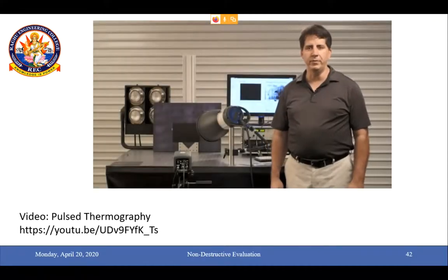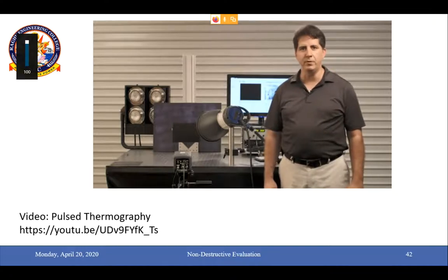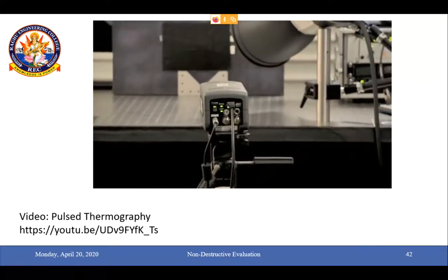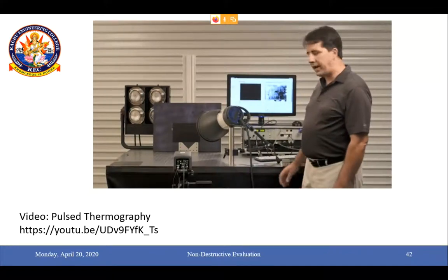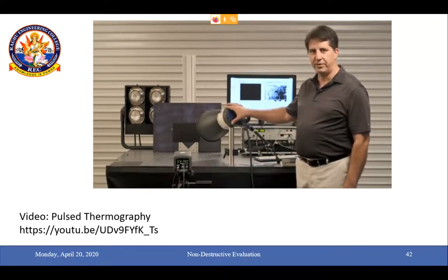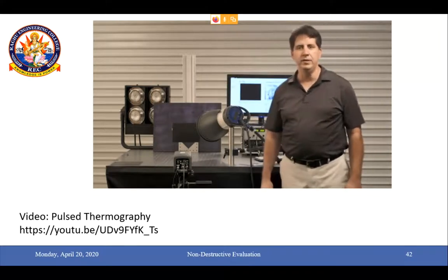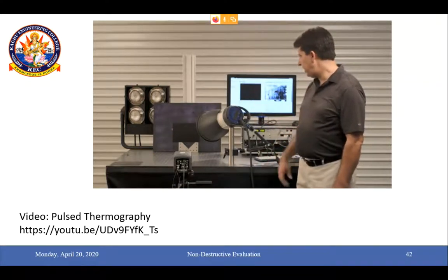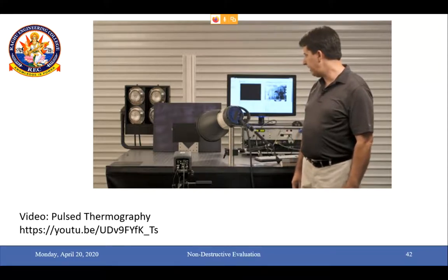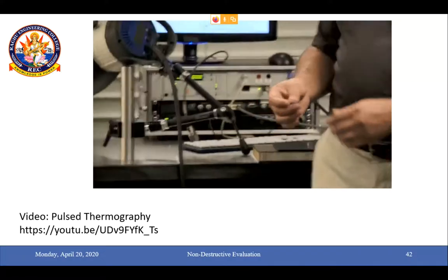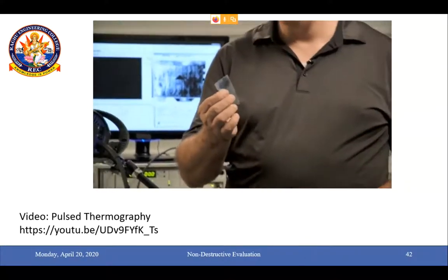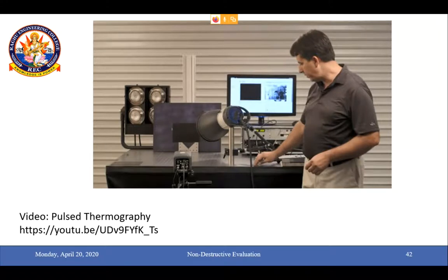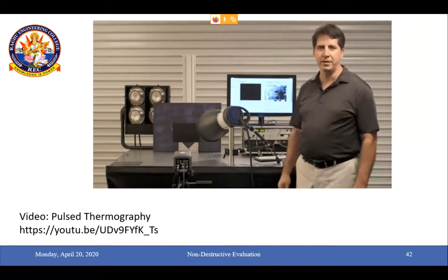Hi, this is John Cabrera for Mobitherm Advanced Thermography Solutions. Today I'm going to be demonstrating for you our pulse thermography non-destructive testing system using the FLIR A6700SC, which is a cooled camera from FLIR, and our IRNDT system fitted with a pulse flash generator, which delivers 6 kilojoules of energy using a commodity flash bulb. So what we've done is we've placed a 3-ply prepreg composite sandwich into which we've placed a defect made of 3-mil poly film, which is the film that covers the cloth before it is assembled. So we're using that to simulate a defect where someone has inadvertently left a contaminant during the assembly of a part.